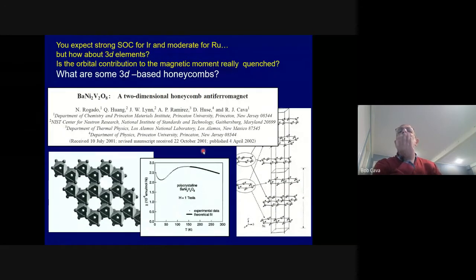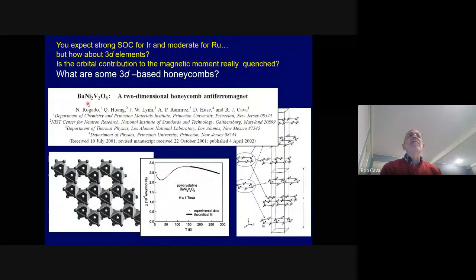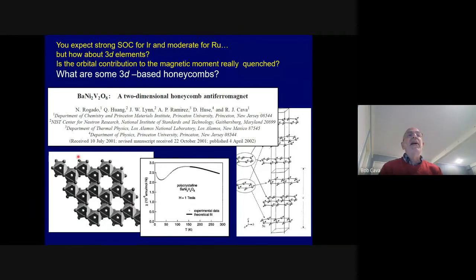So before the theory started coming out, and this was in April 2002, I realized that these materials had honeycombs, materials A, nickel 2 or cobalt 2, P2O8 or VO4 2, something like that, where they're mixtures of a big atom and then transition metal atoms plus other atoms in tetrahedra could make a honeycomb lattice. And that honeycomb lattices are intrinsically interesting. For example, barium nickel 2 V2O8 is an example of something with a spin 1 honeycomb. For the theorists in the audience, they remember spin 1 honeycombs are important systems for topological physics. So we were looking for spin 1 honeycombs back in the day. Found that barium nickel vanadate was one of them, and it eventually magnetically orders.